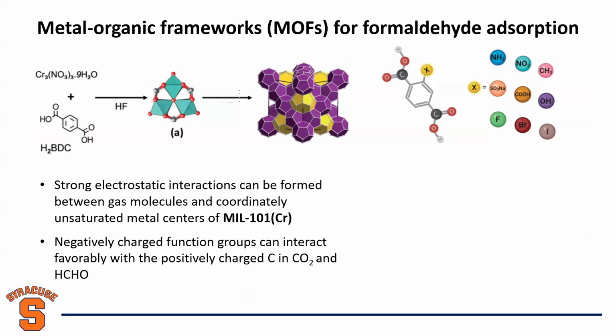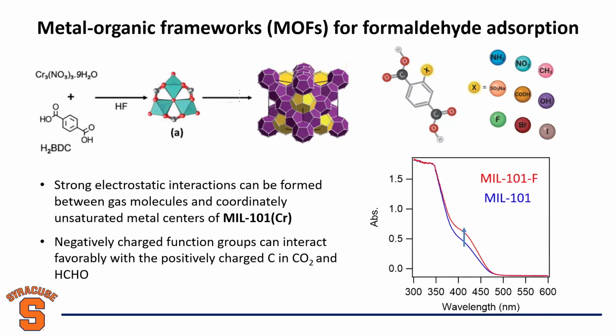Okay. So basically, in a metal organic framework there are two building blocks: metal centers and organic linkers. People reported it can absorb gas molecules, including formaldehyde. But we thought, how can you modify and engineer the common structure to make better filters? So what we did is modify the linker with negatively charged functional groups to increase the polar interactions with formaldehyde and CO2. We can increase the gas separation efficiency. Of course, we can also modify the metal centers. But here, just to present data, we found that after modification with fluorine, we can have more formaldehyde absorbed or separated by the modified MIL-101.